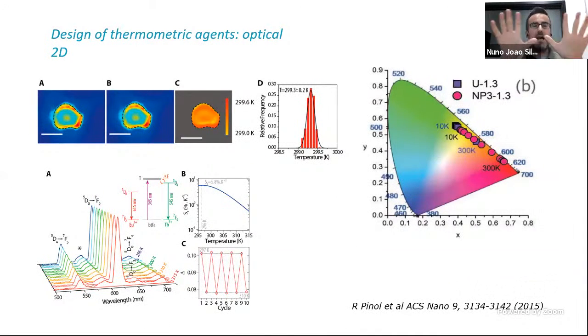Then we got into a temperature map. So we just put these thermometers in an optical microscope. In this optical microscope, we were looking at cells, and we were looking at the fluorescence of these lanthanides. Basically, we had 2 lanthanides, europium, which was giving a red emission, basically constant throughout temperature, and terbium, which was giving this green emission, which was changing with temperature.